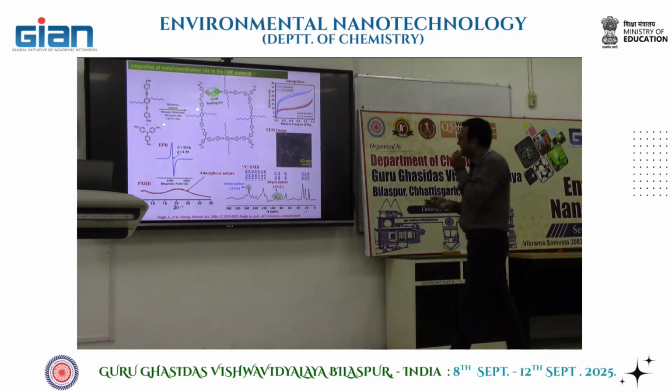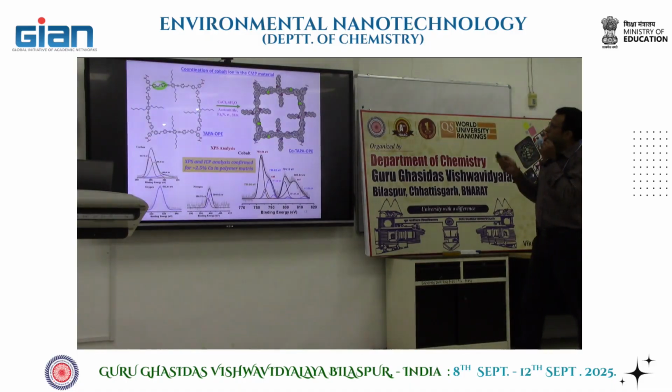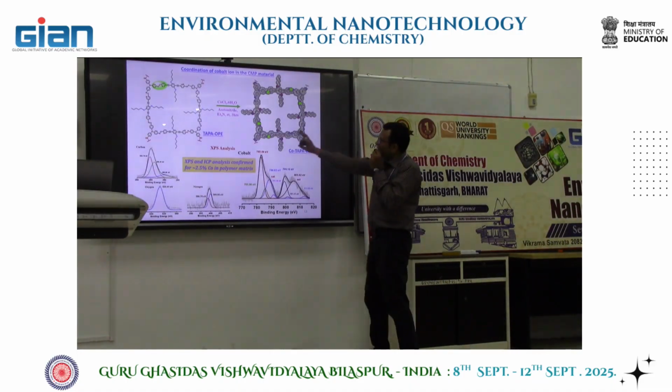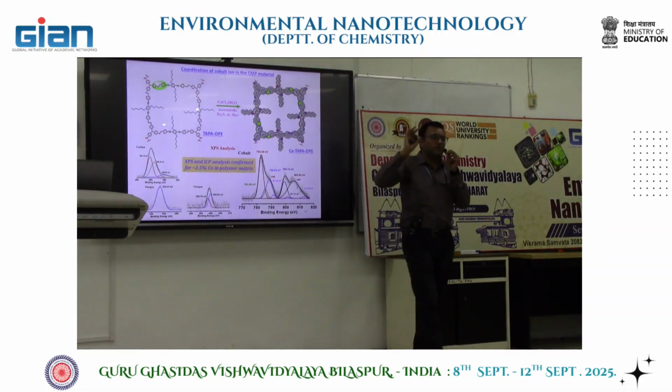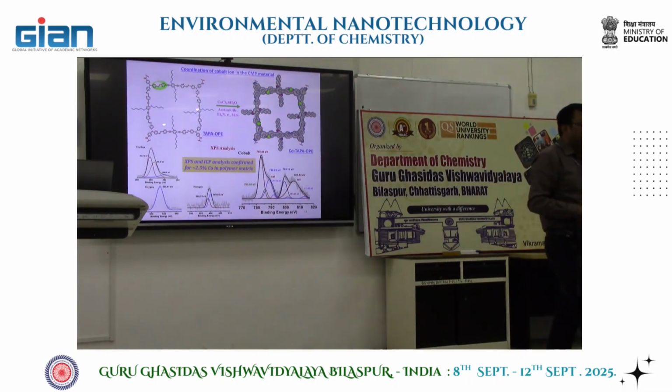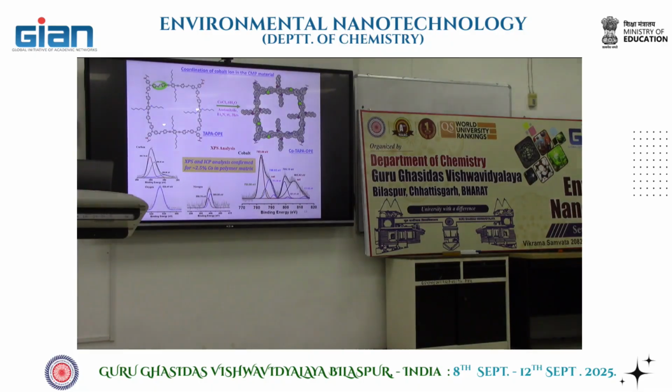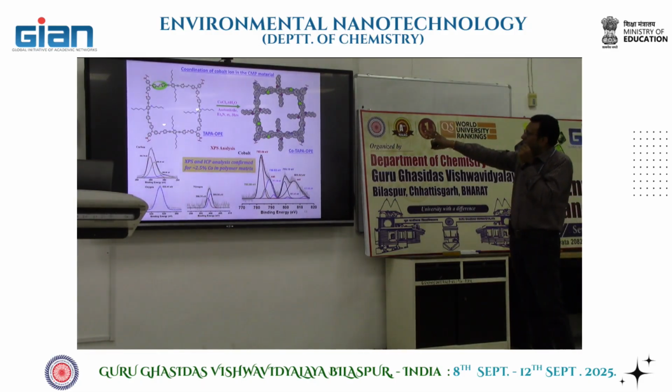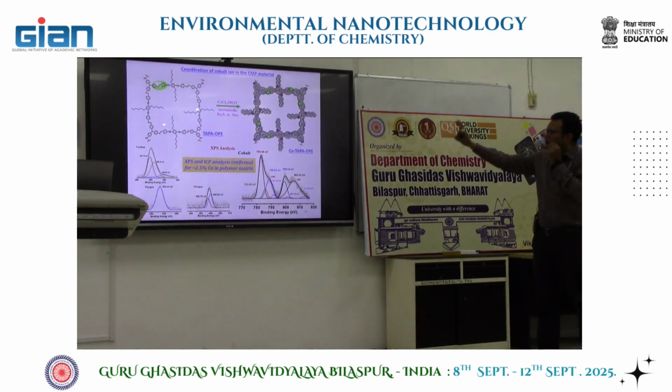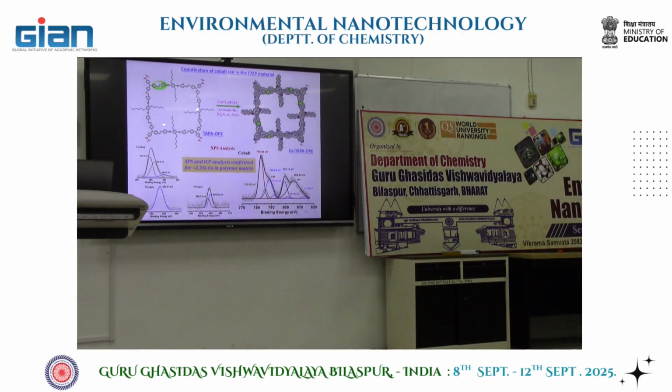After all this characterization, which I am not going through, we found that using similar ways, this gives a cobalt coordinated framework, porous organic polymer. Now we have seen through different analyses that this has almost 2.5% of cobalt chloride, which is bound through these two nitrogens, so basically forming a 5-membered ring kind of thing.